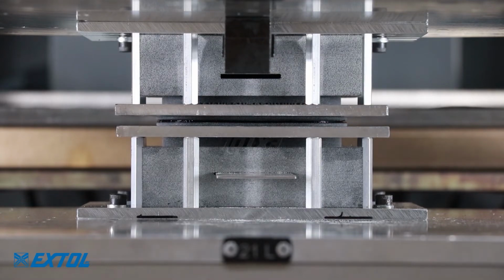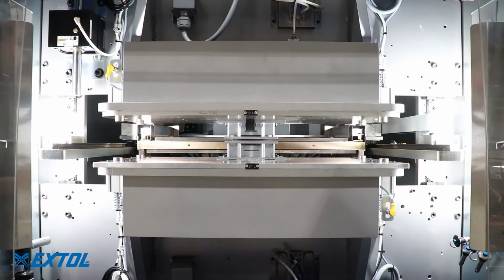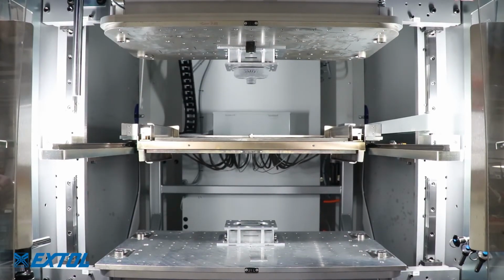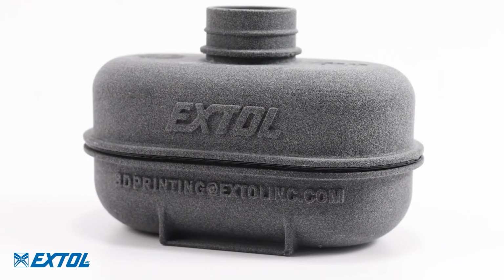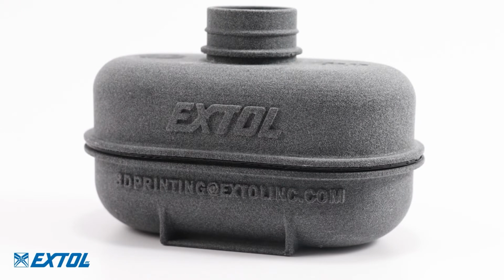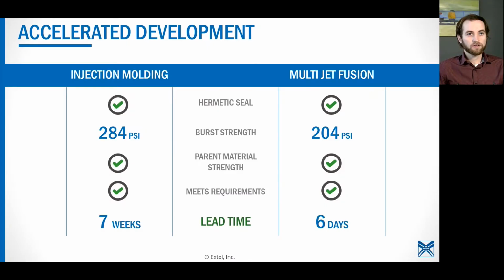This is a strong weld that we use every day with molded parts, and it's really cool to be able to use multi-jet fusion printed parts to bring functional prototypes to reality, combining additive manufacturing and traditional manufacturing welding technology. When comparing injection molded and multi-jet fusion results, we find that the burst strength is reduced slightly due to the different manufacturing process. The multi-jet fusion parts still met our customers' requirements. However, we could alter the part design to increase strength if necessary. And then, of course, the lead time, as mentioned before, goes from weeks to days, and everything else is comparable.